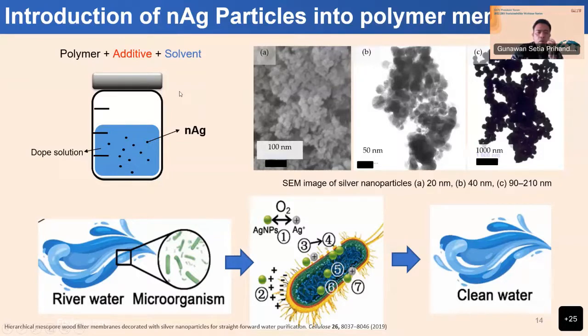It is almost the same way as when we make the solution for the normal membrane. In this case, we just add an additive like nano silver particles. We mix the additive and the solvent, and make sure it's completely mixed in the solvent. When it is completely mixed, we add the polymer, and then we leave it for around 8 hours at a temperature of 60 centigrade. And then after 8 hours we have the dope solution.